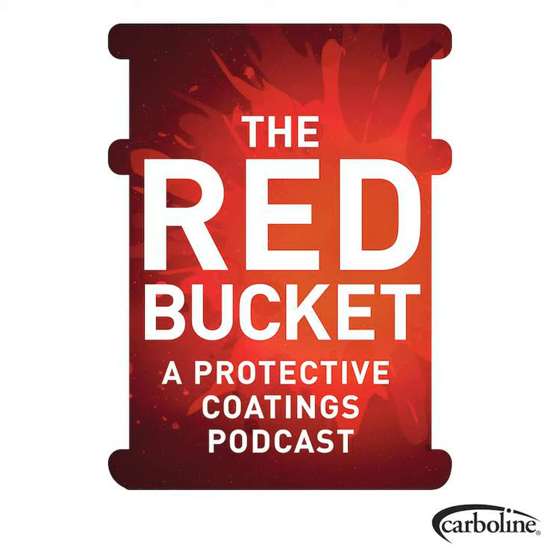the last several years. Yes, and I've seen customer specifications, shipper specifications where they specify a one coat epoxy system, 7 to 9 mils dry film thickness, and then I've seen specifications for a two coat system of the epoxy coating at the same millage, 7 to 9 mils. How long should this last? Ideally, let's say. What do you think? 3 to 5 years? Yeah, kind of what I had.